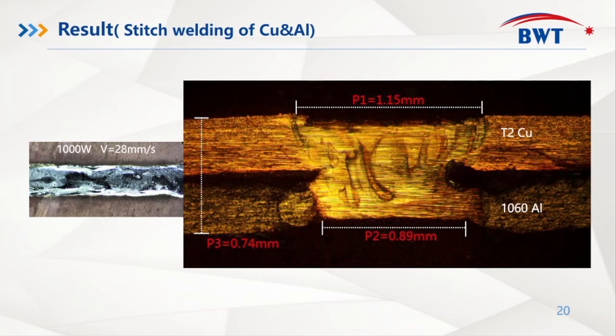In all the tests above, a high quality heat conduction weld and smooth surface on the samples was shown, and the whole process is very stable without splash and all cross sections have no pores.